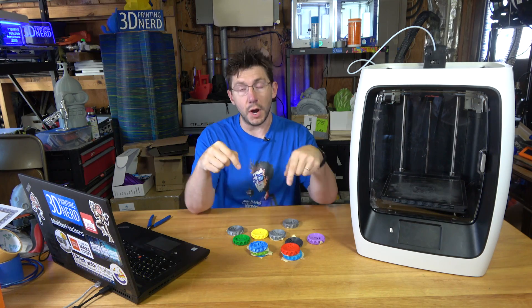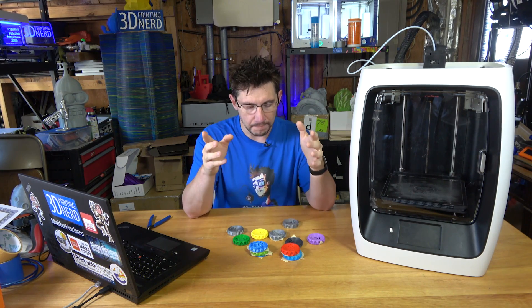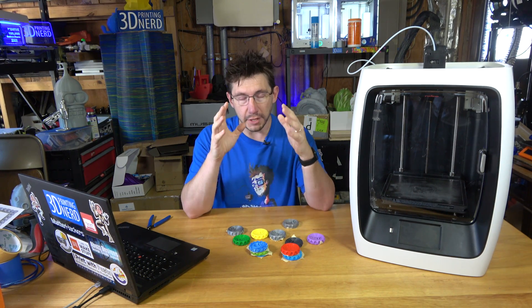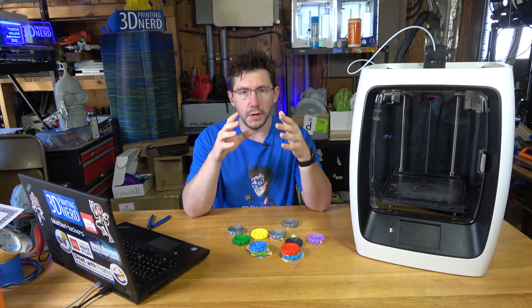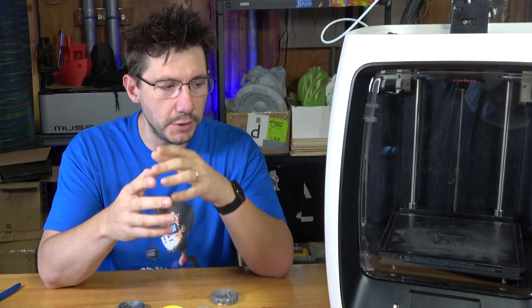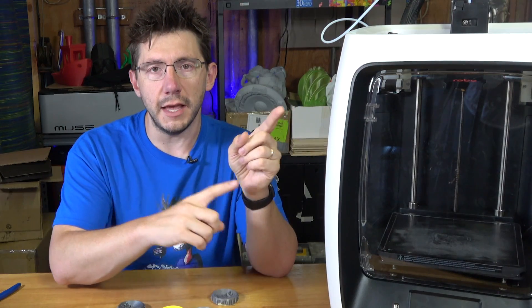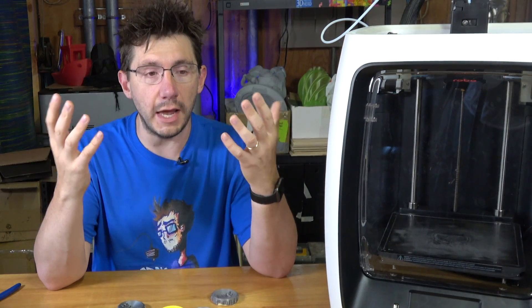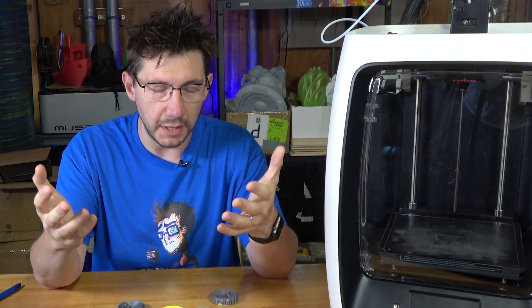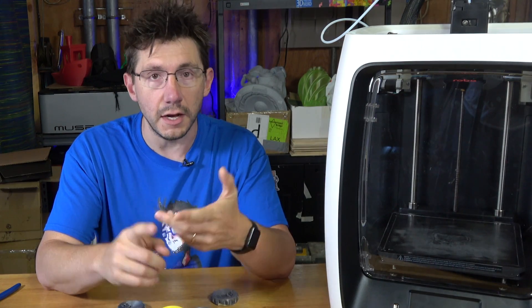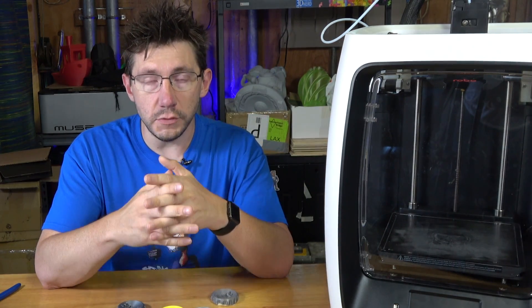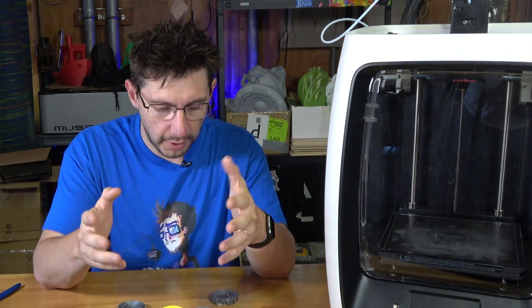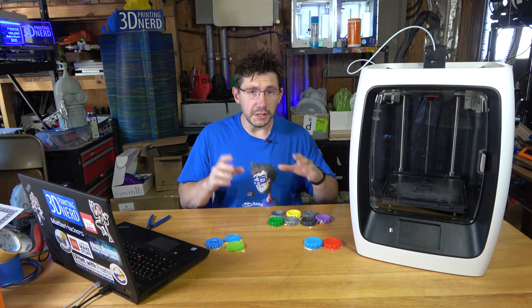I know publicly I've said that I've had some problems with filament, and I know others have as well. So my buddy Josh and I, we decided to do a test. We were going to do a MakerCoin model that was going to exist in G-code on the machine, and then it was going to be a set of parameters I knew that would work for most all PLA. So we're going to do 205C on the nozzle, 60C on the bed, defaults using Cura, and this is what we came up with.